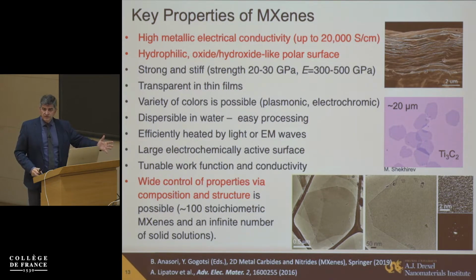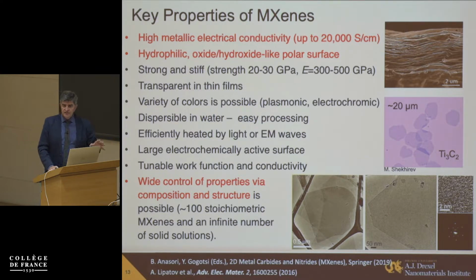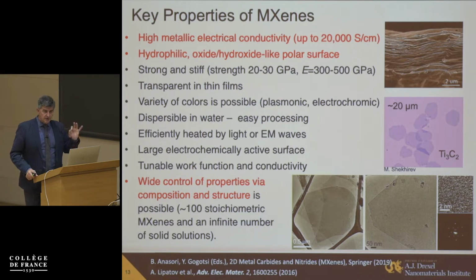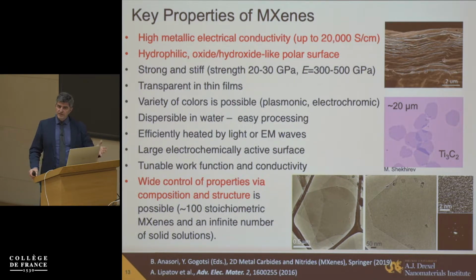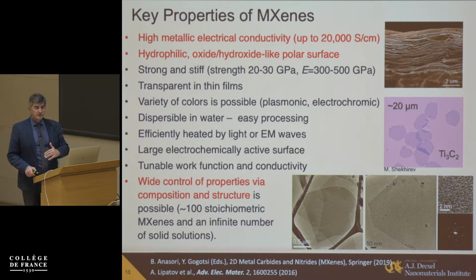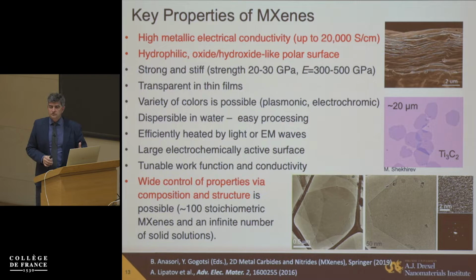You don't need surfactant, unlike for graphene and many other materials, so you can basically assemble it easily. Now, what are typical properties? The majority of MXenes studied today are true metals with a high density of states at the Fermi level and a high concentration of carriers. Remember, even graphene, promoted as a highly conducting material, is a zero band gap semiconductor. You need to create defects or dope it, and by doing so you decrease the conductivity. But it varies within like 4 or 5 orders of magnitude.